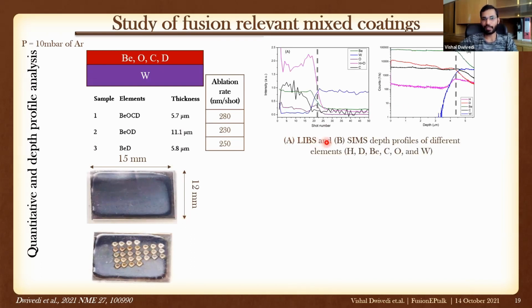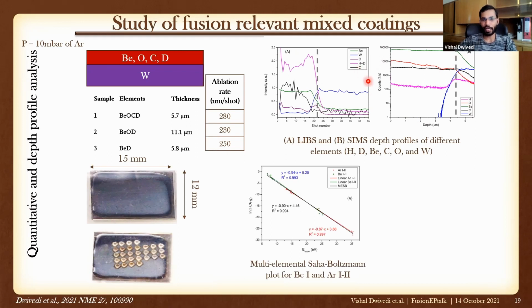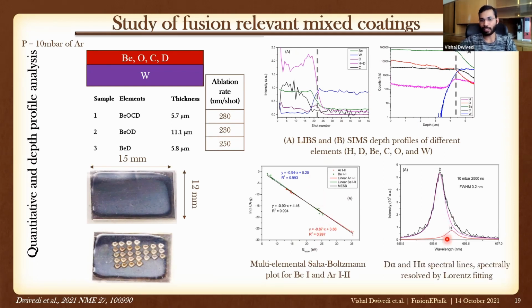We had the LIBS depth profile: beryllium, tungsten, oxygen, carbon, and hydrogen plus deuterium. This was for this specific sample. And we compared this LIBS depth profile with SIMS also. This line represents the coating and substrate. We have this multi-elemental Saha-Boltzmann plot for the evolution of temperature from beryllium and argon spectral lines. And this is the deconvolution of the deuterium and hydrogen line for the calculation of the D/H ratio.